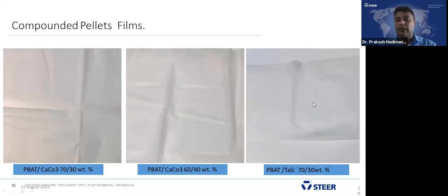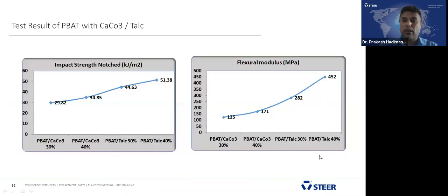was fantastic. And these are the blown film photos. And you see 30% calcium carbonate and 30% talc in both the cases. The results show PBAT with the calcium carbonate and talc separately. At 30% calcium carbonate with PBAT and 40% calcium carbonate, the trend shows a slight addition of calcium carbonate increases the impact strength. You see the increase in the impact strength from 30 kilojoules per meter square to 34.